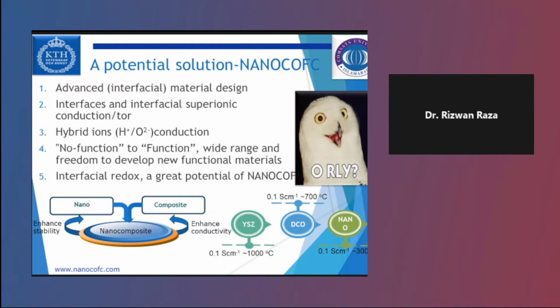That project provided different solutions, but one of the big potential solutions is how we can prepare that material. First, interfacial type of material can be designed, where interfaces and interfacial superionic conductors can be designed. Then you can introduce hybrid ion conductors. Mostly in solid oxide fuel cells, oxygen ion conductors are more important, and common materials can be used as oxygen ion conductors. But if we introduce a hybrid ion conductor, its ionic conductivity can be further enhanced. Some materials are not functional, so if they can be activated, functionalized at the required temperature, that can also be good. So it has been divided into these 5 parts. And then of course interfacial redox is also very important when you are going to use compatible electrodes. These are some of the great potentials of that particular project.